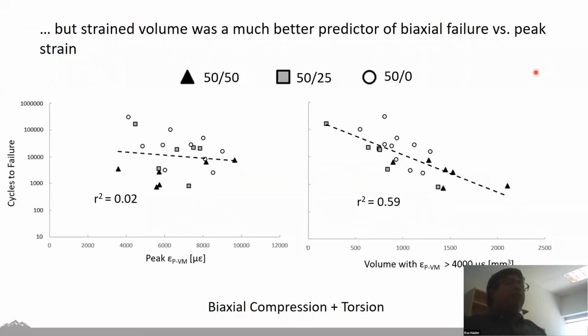However, we saw a completely different situation when we looked at our biaxial test results. Here, peak strain basically did almost nothing for us. It didn't explain any of the variation that we were seeing. And yet the strained volume criteria turned out to be relatively robust. It continued to explain the variation that we were seeing in the biaxial loading case as well. So that's one key finding from all of our simulations.